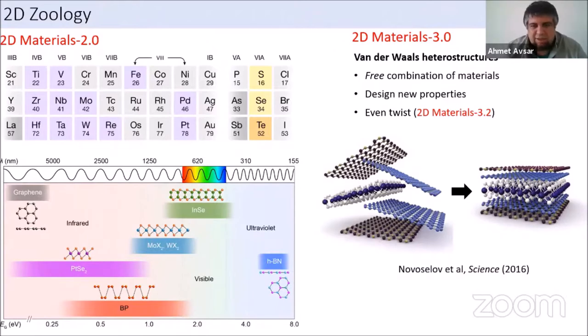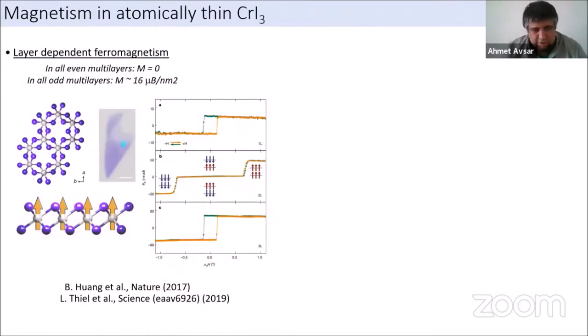The answer was considered to be impossible, but later a group at Washington University and MIT demonstrated that a material called chromium iodide does show magnetism at the monolayer limit. This material is very interesting. At the monolayer and also other odd layers, the material is fully spin polarized. It was shown that in a bilayer, the spin polarizations from both layers cancel each other at zero field, and the material becomes an antiferromagnet.